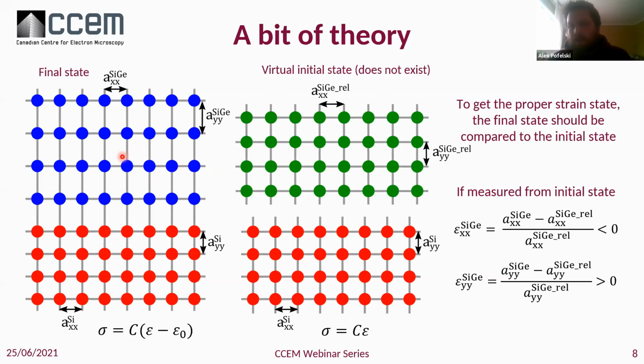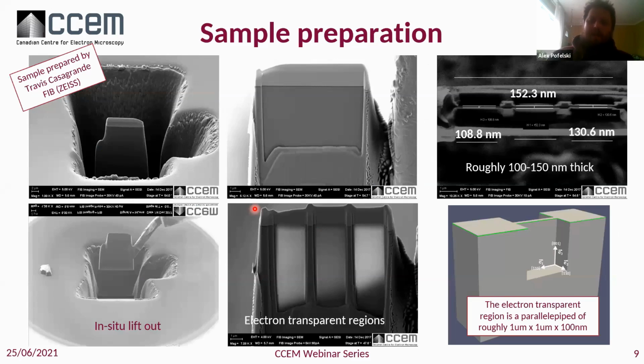usually we like to link it to a stress. So we can't use this easy, simple Hooke's law that we have. We have to make a small correction to take into account that the final state is slightly different from the initial state of the silicon. And with that, the interpretation becomes physical and easy to do. But this is something we have to keep in mind, because this happens all the time, whenever we do a relative strain characterization method. So this is one thing very important to keep in mind, and we will come back to it throughout the presentation.